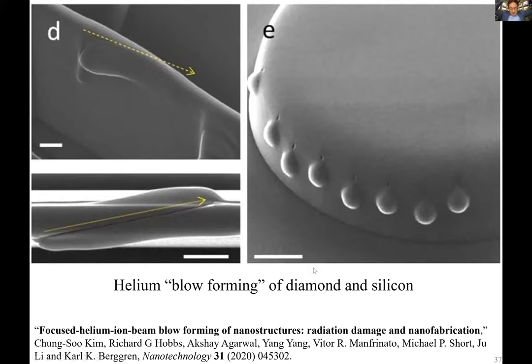And you can also use an ion beam to create strain in materials. This is a very interesting collaboration with Professor Berggren at MIT, where we showed that with a very focused helium ion beam, we can inject bubbles near the surface, and that's going to blow form it, almost like blow forming a glass. And then you can impart a few percent tensile strain in this region. Of course the trick is how can you create strain in these bubbles, or these kinds of shaped bubbles, without creating damage in the regions themselves. So this is still ongoing research. It illustrates what nano beam radiation can do.